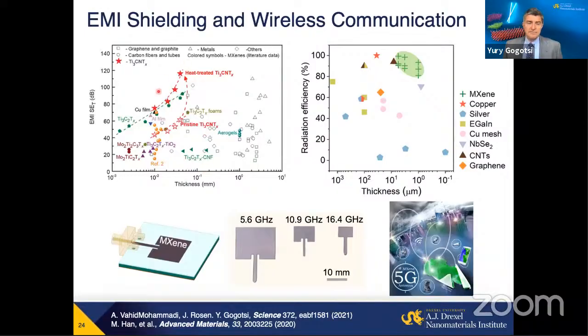But a year ago, in the August 2020 issue of Science, we showed that titanium carbonitride Ti3CNTx, which is actually less conducting than titanium carbide Ti3C2, outperforms metals like copper, although traditionally it's considered that conductivity is the key issue for shielding. So it shows that there is interesting new physics, when the waves interact discretely with all these layers of the material and get absorbed or reflected more efficiently than in metals. And this has truly been a breakthrough in the field.